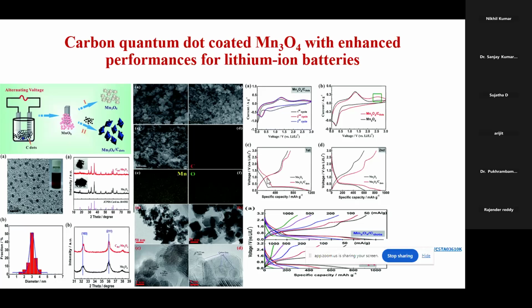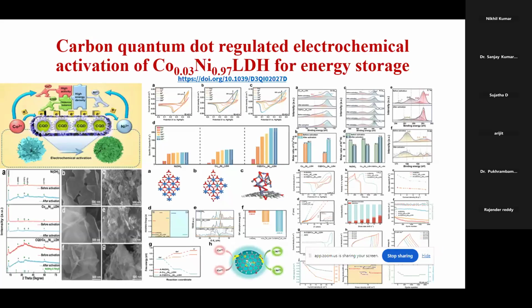good voltage. Then another work, like carbon quantum dots regulated with electrochemical activation of cobalt nickel LDH. LDH usually using for water splitting applications. Here energy storage also. Energy conversion usually people using with LDH, we can do it for energy storage application also. With this electrochemical activation we can incorporate this CQD to achieve this high activity, balance and high energy density. So with this things we can add it into this cobalt nickel LDH, this CQD also. So we can see this XRD peak and TEM images, the formation of this one.